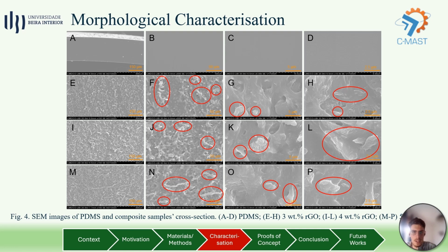Now, starting with the characterization techniques, we began by observing the sample's morphology by SEM, where, unlike pristine PDMS, which had a smooth surface without pores or damage, the surface of the composites had a much more crumpled, wrinkled, and flaky-like appearance, all due to the presence of rGO. In addition, while for 3% the filler's dispersion was uniform and well bonded to the matrix, as the rGO content increased, the filler's density and the porosity increased as well, along with the glomerates that began to appear in more quantity and size, which of course will affect the mechanical and electrical performance past the saturation point.